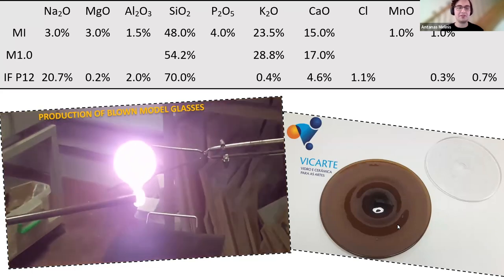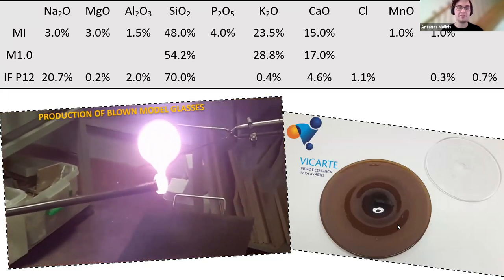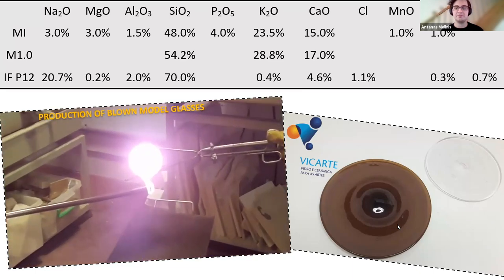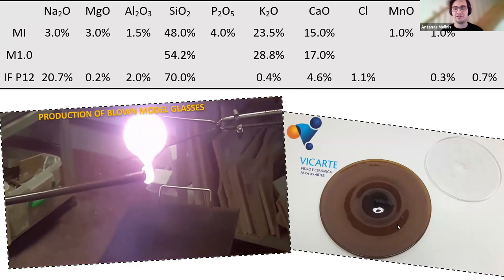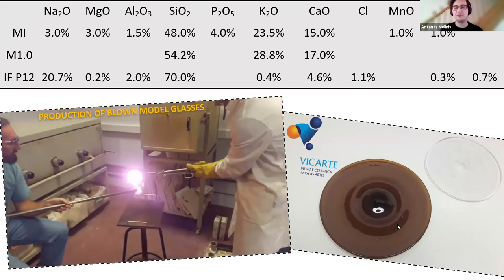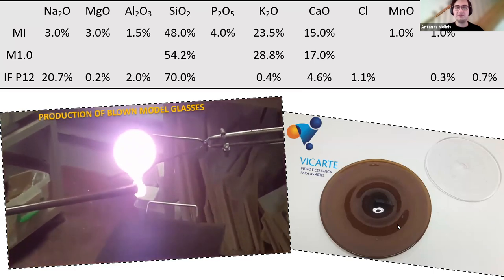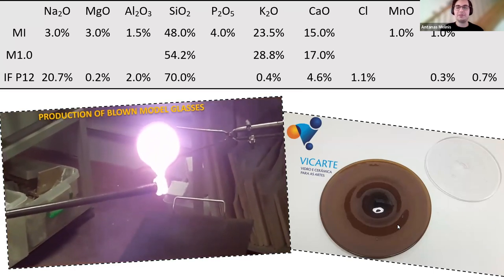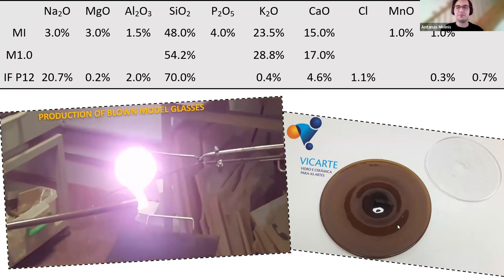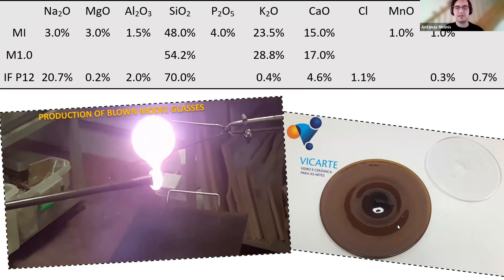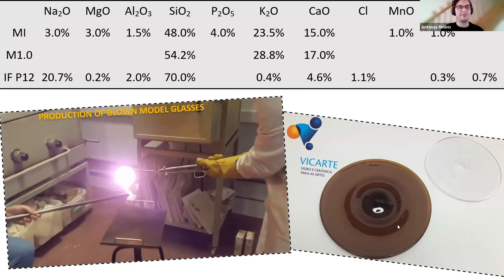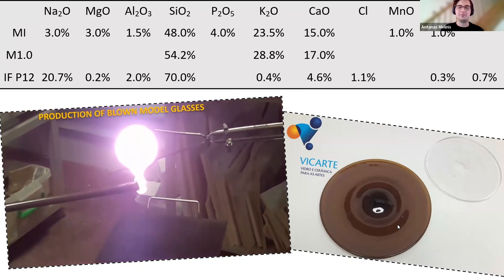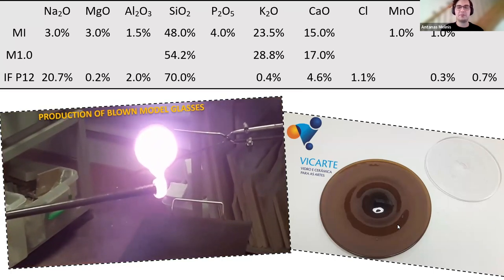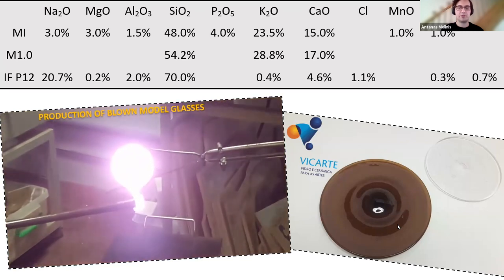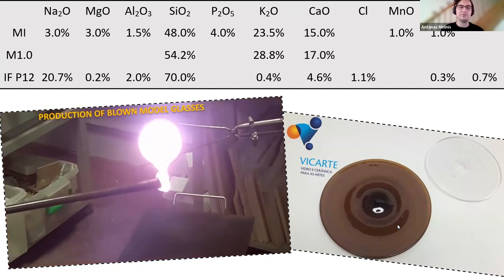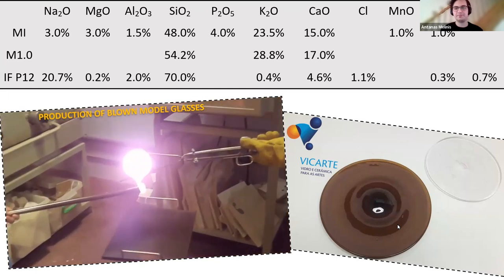So we reproduced some model glasses, the compositions of which you can see on top. The first two were widely used by German researchers, and they were chosen because it would allow for easier comparison with the results of their studies. They are meant to model the behavior of medieval European glasses, whereas the third one, called IFP12, is a model glass based on the composition from a Roman Iulia Felix shipwreck, which is also a relatively unstable glass for its time by composition.